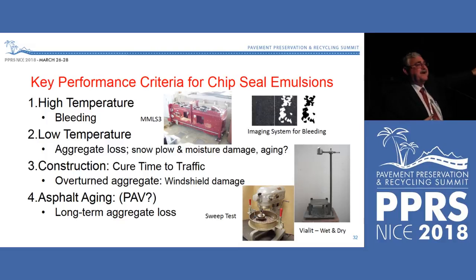For all the performance criteria, he can measure image bleeding, and therefore we can make decisions on the rheology of the material at high temperatures where that bleeding doesn't happen. Same thing for low temperature with aggregate loss. He's looking at a number of tests, including the Vialit ball drop test. And we don't know if we need moisture damage or not for chip seals, so we can condition that ball drop test material with moisture. We can do it dry.